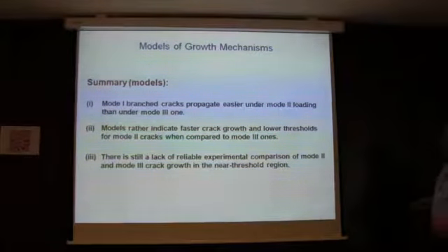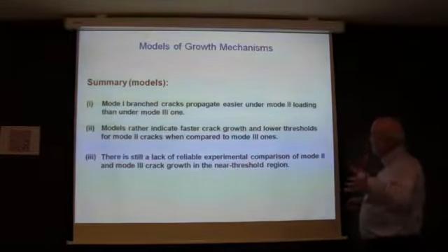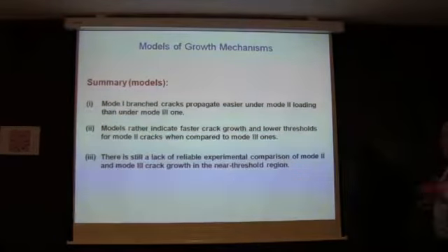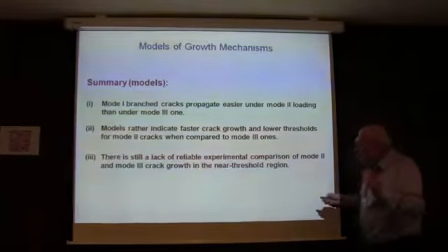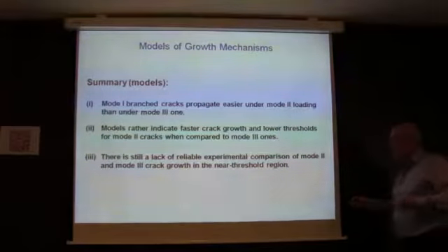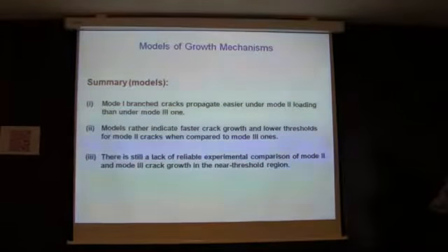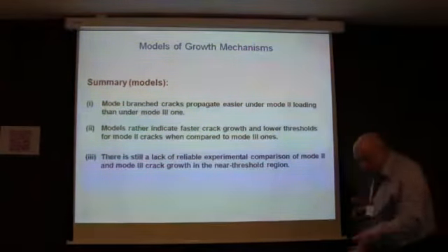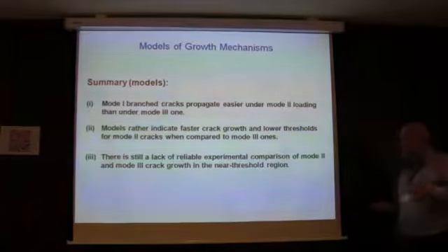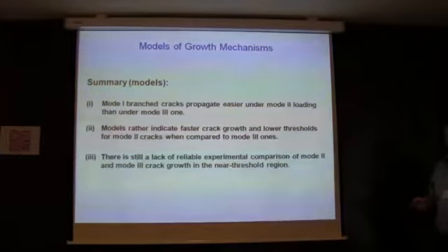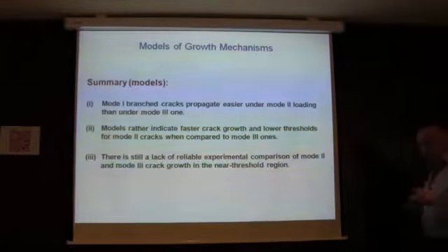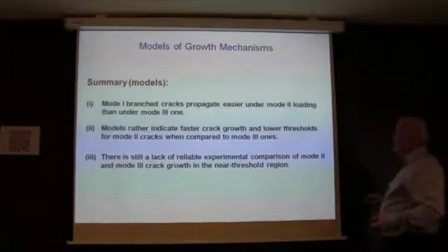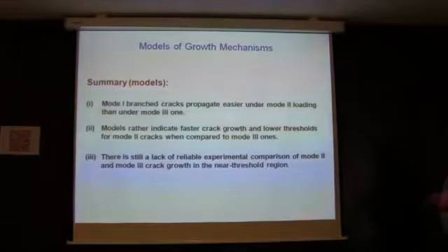Okay, so a summary about the models. A mode 1 branch can propagate more easily under mode 2 loading than under mode 3. Models rather indicate faster crack growth and lower thresholds for mode 2 cracks when compared to mode 3 ones. And there is still a lack of reliable experimental comparison of mode 2 and mode 3 crack growth in the near threshold region. So we focused on this, and the other problem is to find the effective values without shear closure. But it's not so easy.